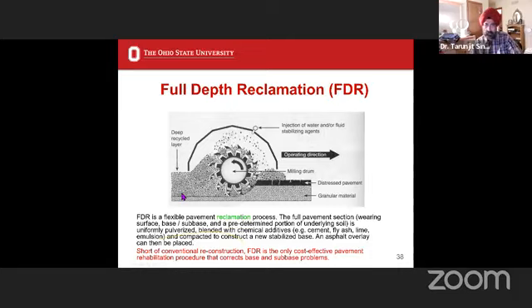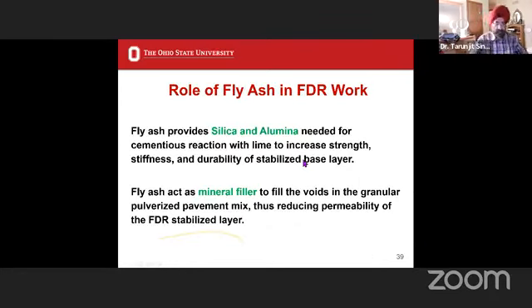And what we are trying to do in this case is use the following: cement, fly ash, lime, and emulsion to create a new base. And then the asphalt that was sent, part of it comes back here, or some other project's asphalt comes on top of this. Short of full reconstruction, this is the most cost-effective method to correct base and subbase problems. What does fly ash do? Fly ash provides silica and alumina, which is needed for cementitious reactions.